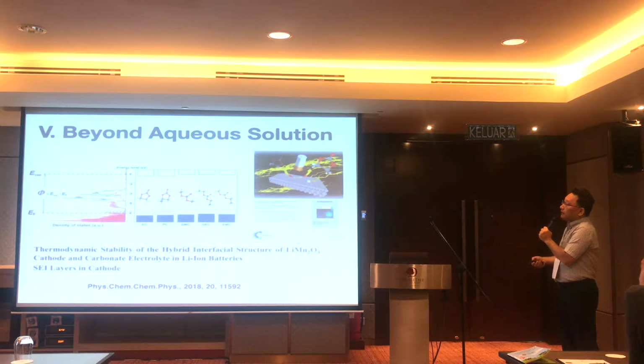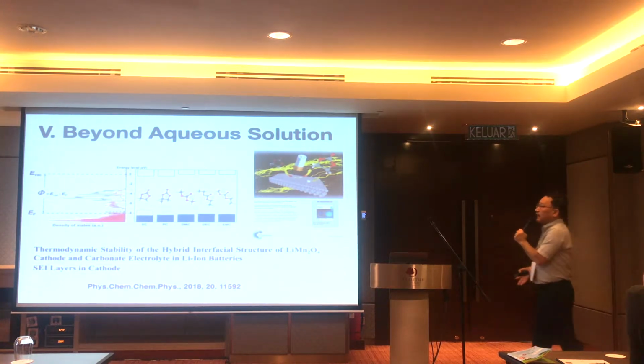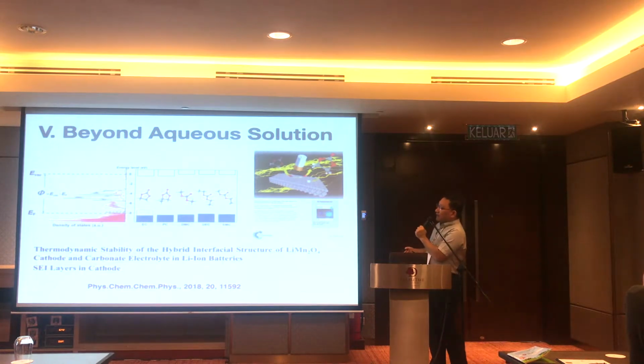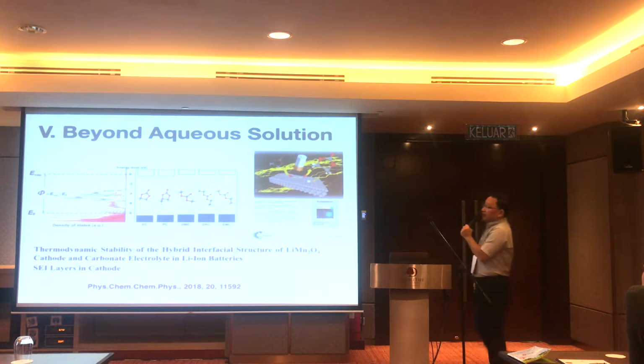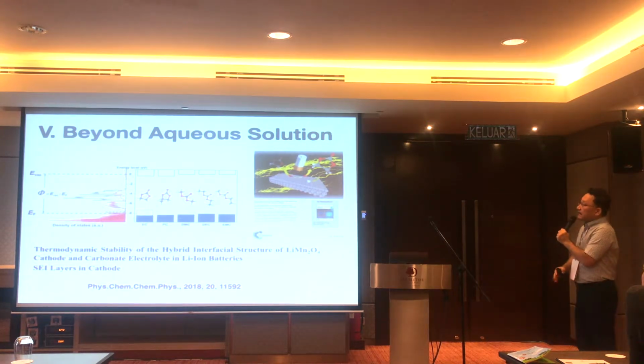Now, these days I'm working on different materials. For example, lithium manganese oxide. This is an important cathode material of lithium-ion batteries. And what happens if this oxide material is exposed to carbonate electrolyte? There are oxidation and reduction, redox reactions between the cathode material and the electrolyte. The electrolyte decays through certain reactions with the electrode, and there are instability issues in lithium-ion batteries. This was also chosen as a cover of the journal.